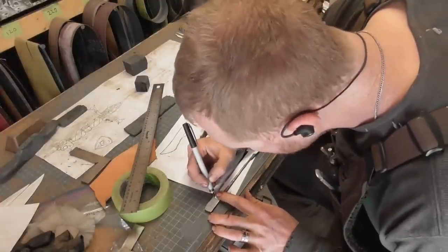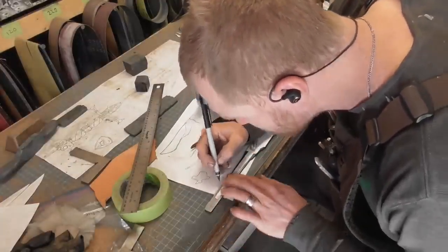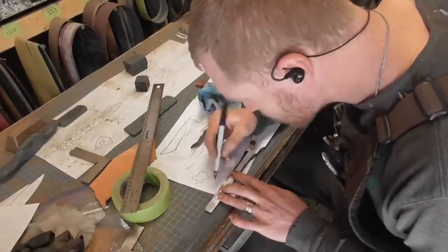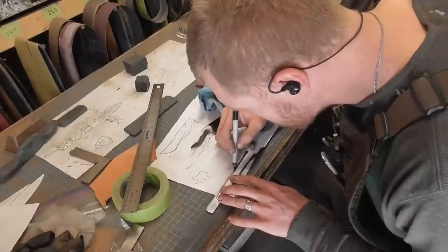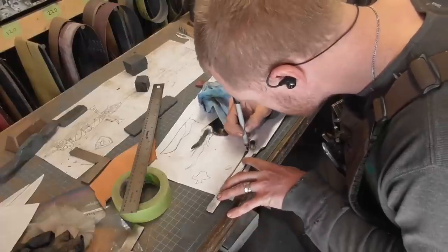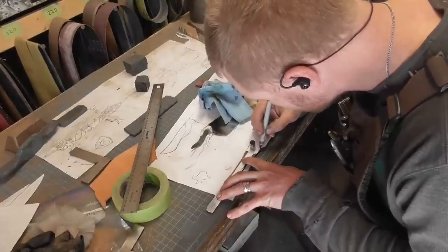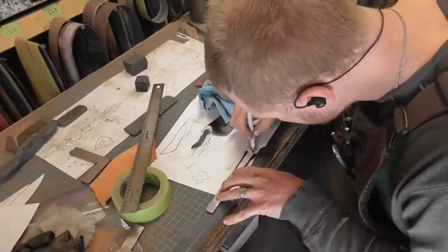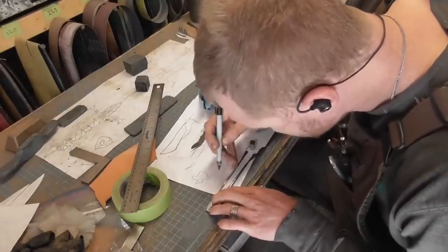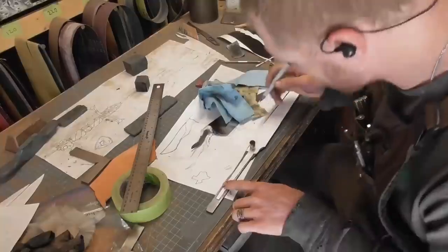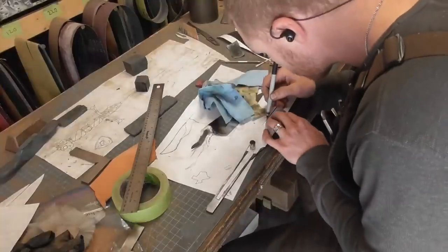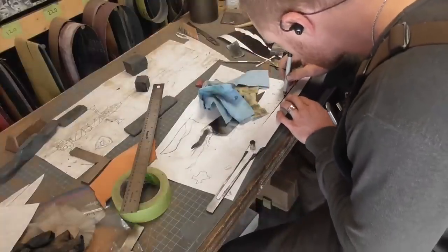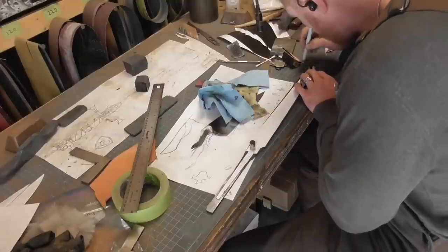Also, depending on the pattern that you're doing, you might want to do a pre-etch to reveal that pattern. I did that here because this is a 4-bar twist, and I wanted the center of the bars, that midline, to be right on the ridge of where the dagger grinds were going to be. So that way I could actually trace over the center line of the pattern in the Damascus and then line up the center line of the dagger with that pattern. Once that's all done and traced on, then I go over to the grinder and grind that all to shape.